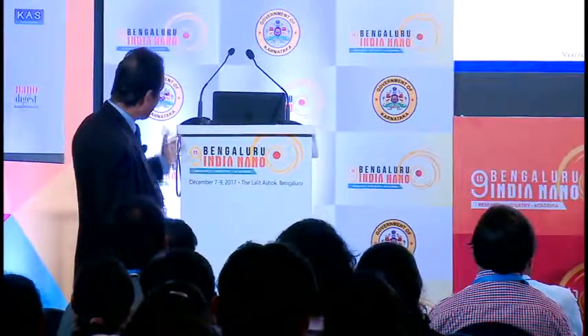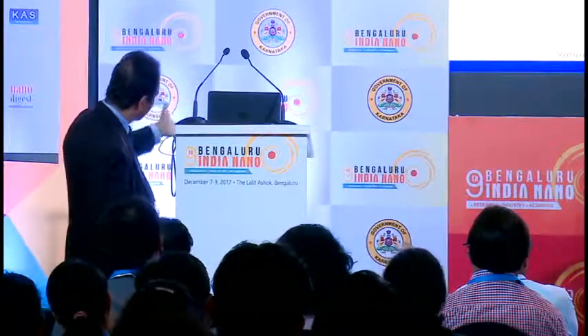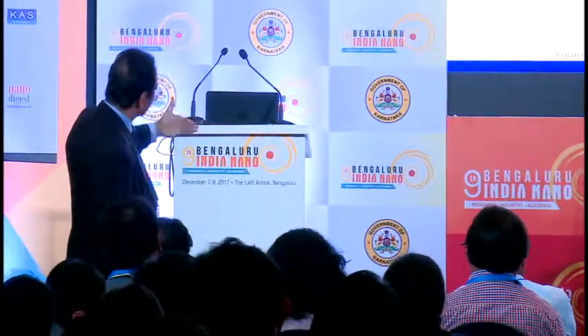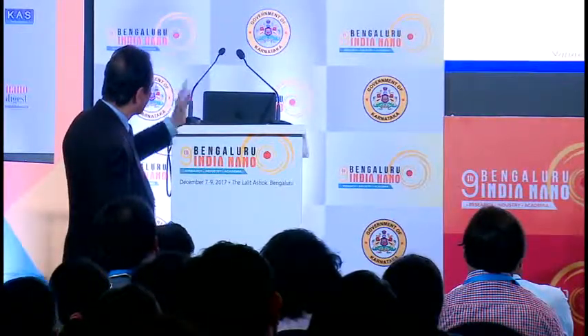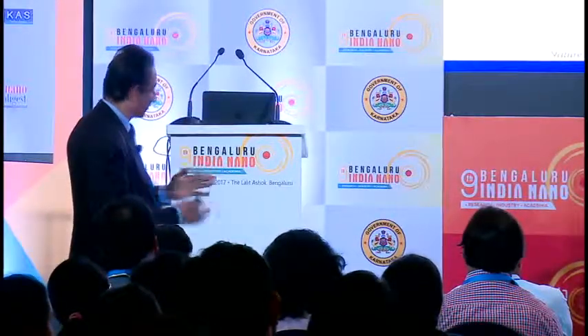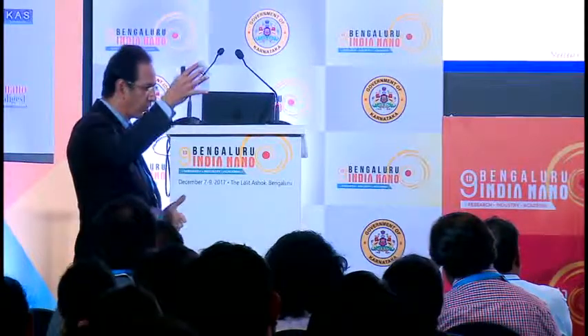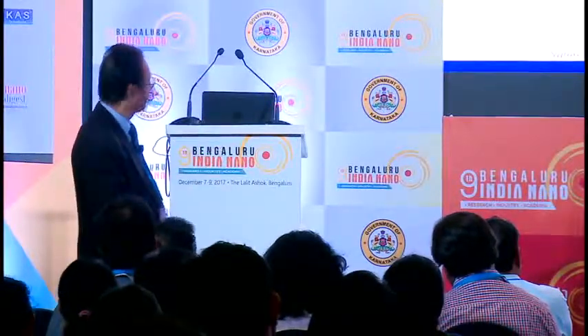Okay? So what happens is, when you look at the resistance of this device as a function of voltage, you see it has two resistive states given by this hysteresis curve. Okay? And this has to do with the polarization of the dielectric. The dielectric is polarized one way, you get one resistance, polarize the other way, you get the other resistance.